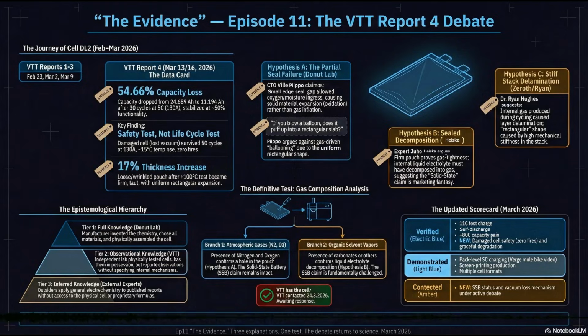Okay, and hypothesis A also perfectly explains the degradation curve, doesn't it? Remember that 50% capacity plateau? Yes, the capacity curve matches a slow ingress mechanism perfectly. Think of the battery as a thick book. The exposed half of the cell near the edge breach oxidized and degraded rapidly as the atmospheric exposure slowly moved inward, page by page, over those first 26 cycles. That explains the cliff edge drop.